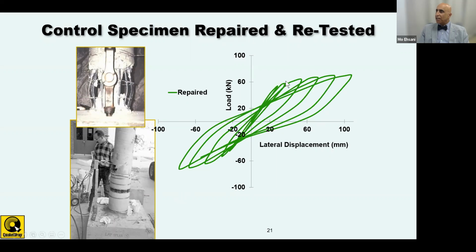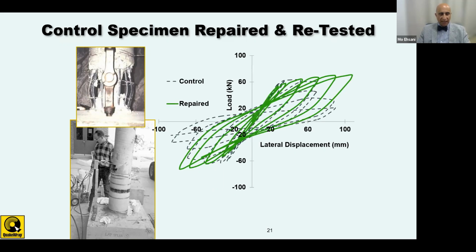You see that in this case, the load keeps on increasing with every cycle. As we push, it keeps on taking more load, and we ultimately had to stop the test because we ran out of displacement capacity of our equipment. The column had not failed per se. In comparison, if I put on top of that, the dashed line shows the original specimen that you saw on the last slide. After it was damaged and we fixed it, we get a significantly improved behavior with this type of repair.